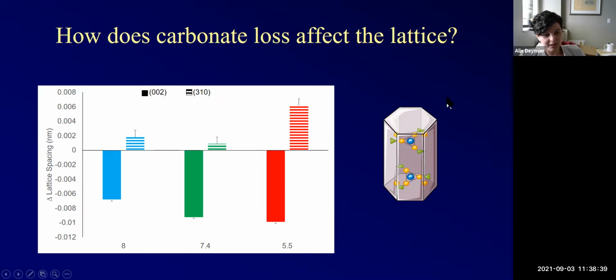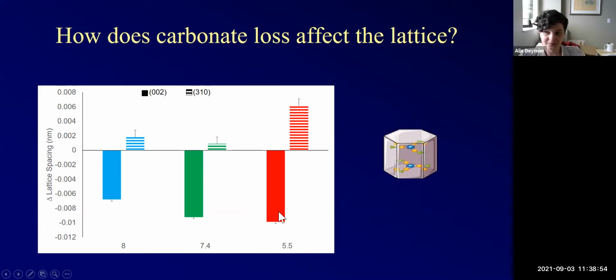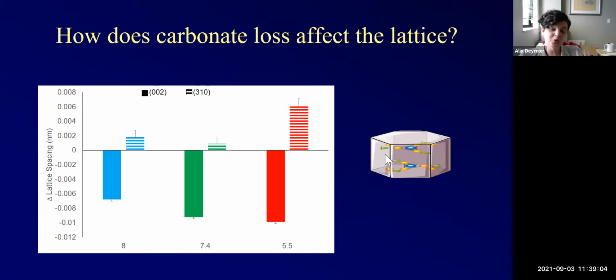If we look at the unit cell of hydroxyapatite or carbonated apatite, that represents this long axis, which is the C-axis. And what you can see is after acid, we actually have a decrease or a compression of the C-axis. We also see that this, the 310, which is the A-axis or the horizontal axis, has an expansion. So just by putting these crystals in slightly acidic solutions for 3 days, we see that the lattice spacing has changed as well as the composition of these crystals.